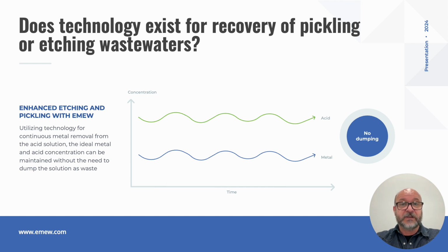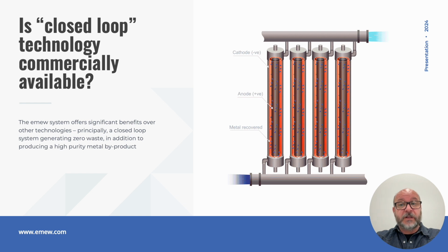The emew smart system electrowinning technology can be utilized in copper or brass pickling processes to recover 100% of the spent pickling or etching solution. In the emew process, the spent solution is sent directly to the recovery process where copper is recovered in a high purity metallic form that is suitable for either on-site reuse or as a saleable byproduct. And the acid component is then recycled directly back to the process for reuse with zero losses or volume adjustment.